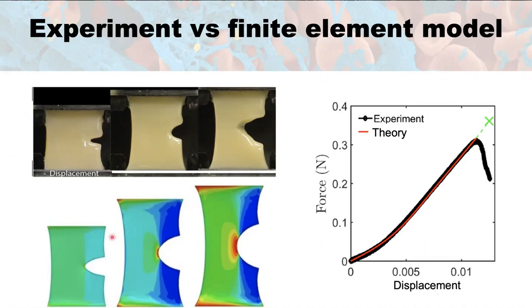And we're able to see that we see a similar effect in the finite element model. If we overlay these force displacement curves, we can see that the experimental curve is in black and the theoretical curve is in red. And you see that we have a good alignment between experiment and theory.